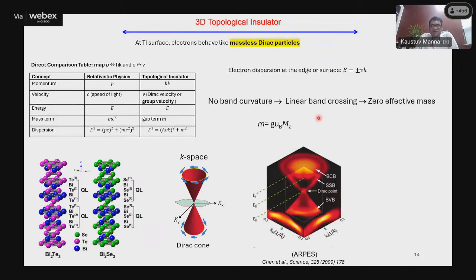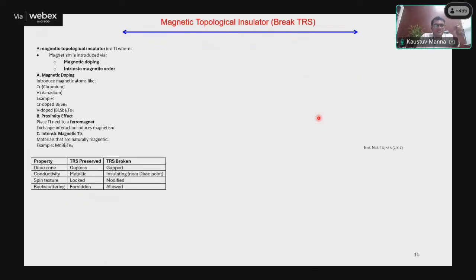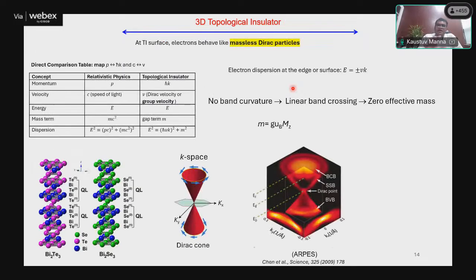So this is the picture of a 3D topological insulator, and we have the linear band crossing, whereas the carriers, the Dirac fermions, have zero effective mass. Next, as I said, of the ingredients which protect the topological insulator, one of the most important is time reversal symmetry. That is the M term. The M term should not be present, so that there is no net moment.